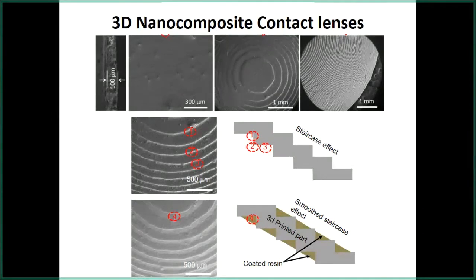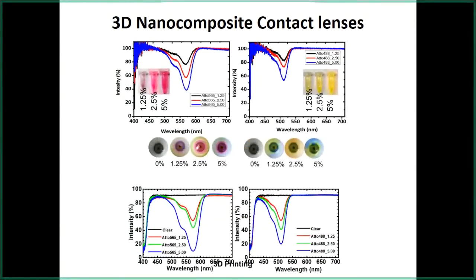Now, with this process, we are printing nanocomposite contact lenses. We are printing these tinted contact lenses as well. So this is a resin that we have mixed with our dyes, like Atto 565, and this is Atto 488. There is an issue over here that I will highlight a bit later. But these are our resins which are previously transparent, but you can mix different concentrations of our dyes, and we can now 3D print contact lenses which are either transparent or tinted. We can control the tinting by controlling the concentration very easily. We can repeat the process very quickly.